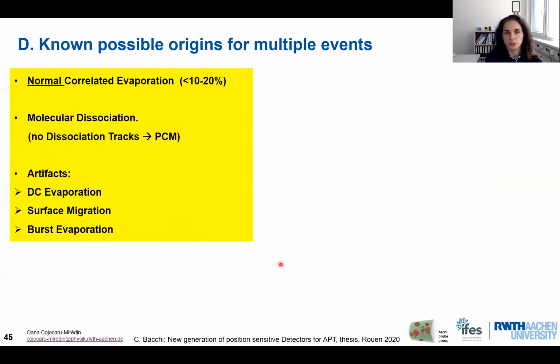So what are the possible origins of the multiple events? As I said, correlated evaporation or molecular dissociation, but we know that there are some phase change materials where we have very little or no dissociation tracks on the correlation histogram, which means that molecular dissociation alone cannot be the single reason for the multiple events. Then we also have artifacts which can explain the formation of multiple events: DC evaporation, surface migration, and burst evaporation. Knowing that in our case the parameters used were the optimal ones, these kinds of effects had not been observed during our experiments. Therefore, I'm not going to speak too much about these artifacts, but there are papers in the literature that discuss them as a reason for the presence of multiple events.